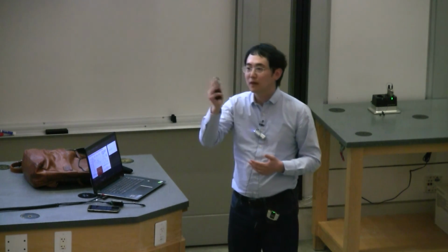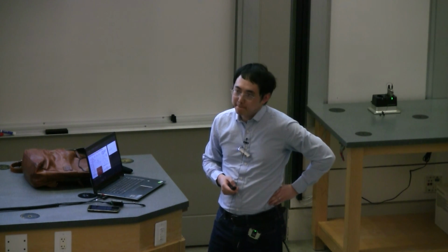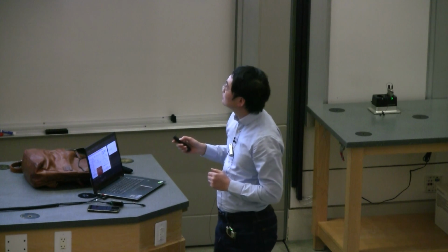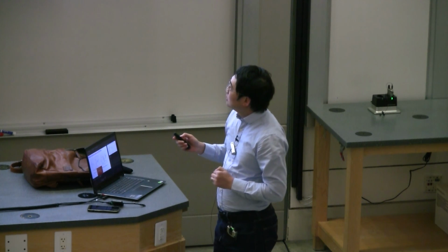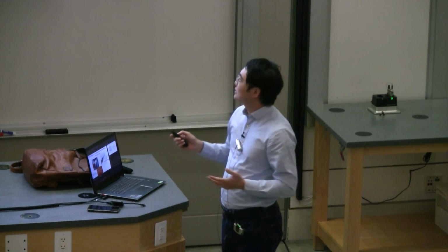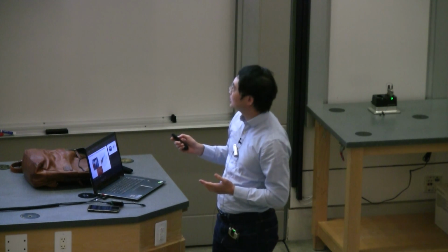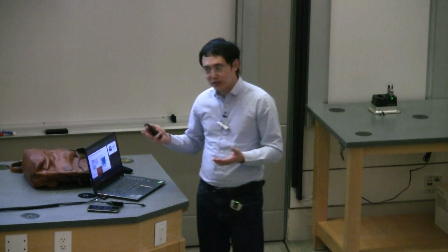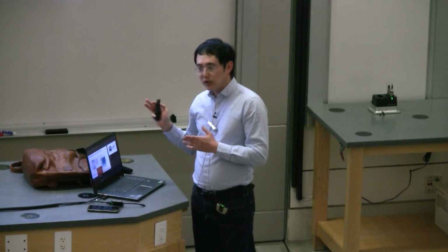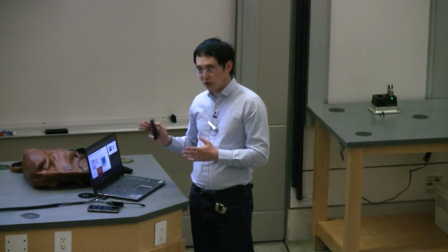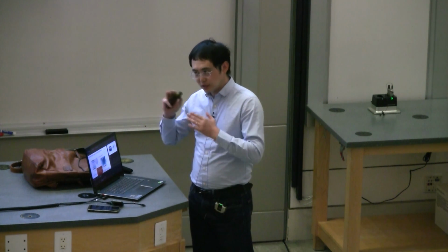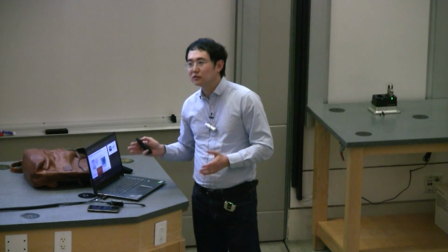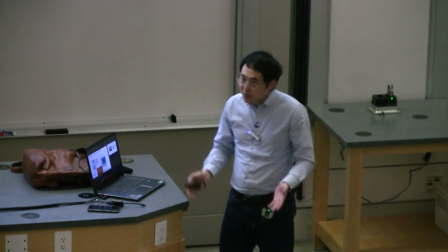Last question. So in the 5-layer plus unaligned HBN on both ends, there's no integer quantum Hall. Is that right? Yeah, so we do have a sample that doesn't have Moiré with HBN, and we don't have a conclusion yet, but so far there's no integer or fractional quantum anomalous Hall at the temperature we have examined. Whether they will show up at an even lower temperature, I don't know.